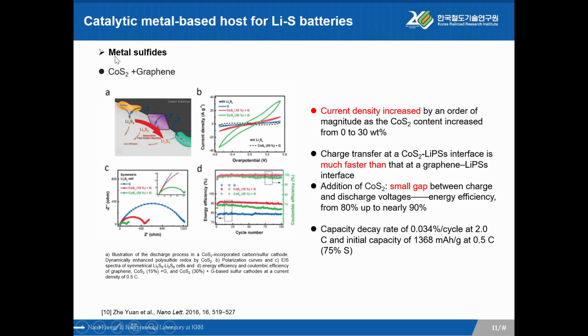This is metal sulfides, or CoS2. CoS2 also has a similar performance, higher current density, and faster charge transfer, from EIS we can say. It has a good stability, capacity decrease ratio just 0.034% per cycle at 2 C-rate. And under the catalyst, there is a small gap between charge and discharge voltage. It means reversibility is very good.